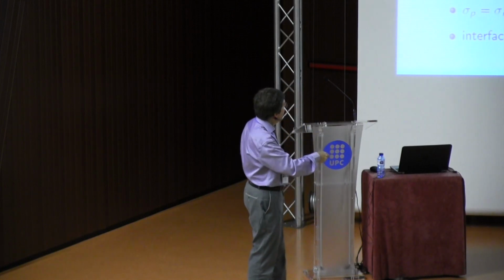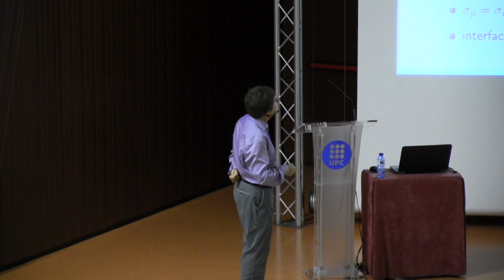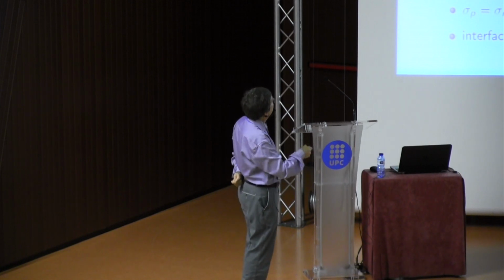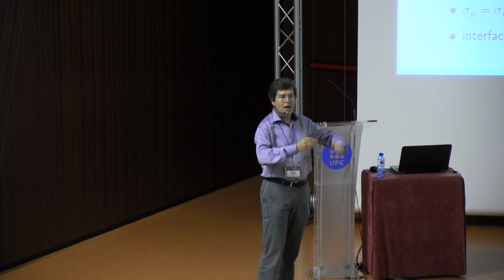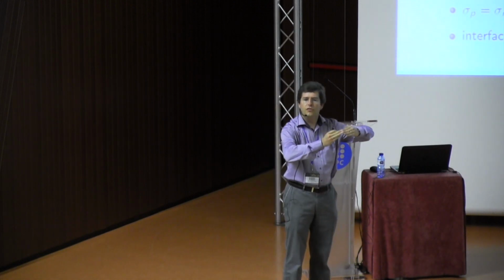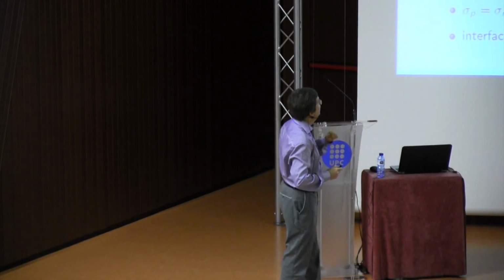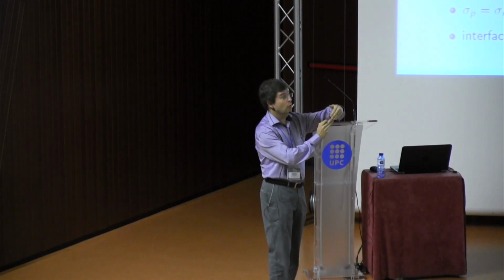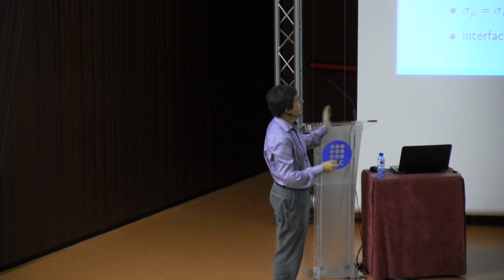And if you solve the differential equation here, you will have a sinus function here and an exponential function here. You have conditions at the interface of continuity of microplastic strain and of the higher order tractions. They are also continuous, and this gives you the profile.